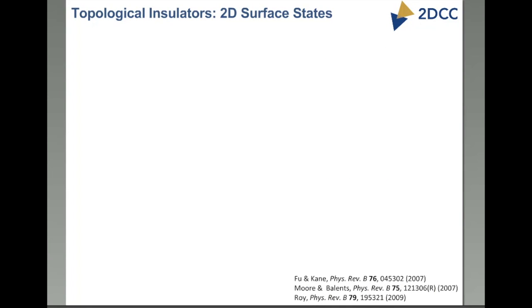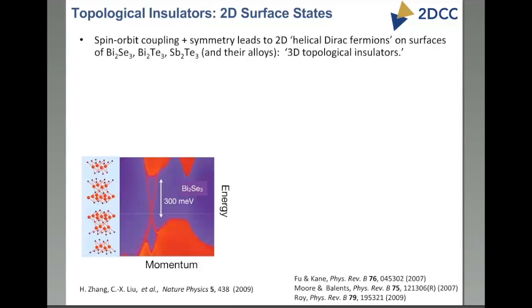Now, let me start going through some of these classes of materials and first talk about the physical properties and phenomena in one class of materials that are close to my heart right now, that my group has been studying for quite a few years. These are the materials known as topological insulators. And here, the 2D is really referring to the surface states. The reason these materials are interesting is that if you take a material like bismuth selenide or bismuth telluride, there's a very strong spin-orbit coupling that plays a role in determining the band structure. If you combine this with fundamental symmetry, with the presence of time reversal symmetry, this leads to states on the surface which span the gap of the semiconductor.